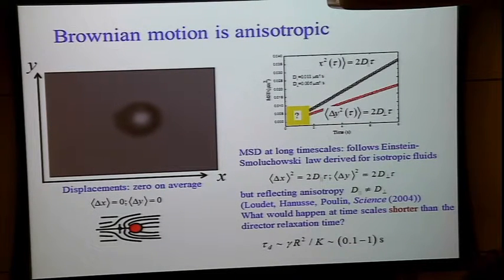That is good, and that is understandable, because we have anisotropy. The parallel displacement is parallel to the director, and the viscosity is smaller than in the perpendicular direction, when the motion has to meet the liquid crystal molecules from the side.